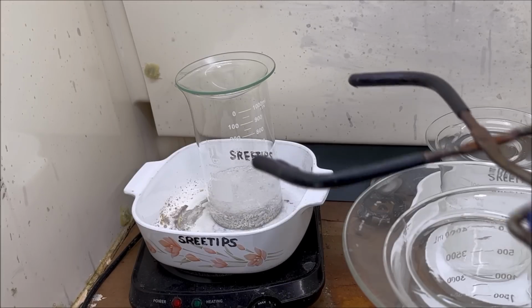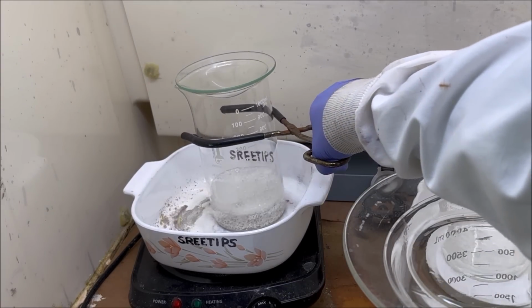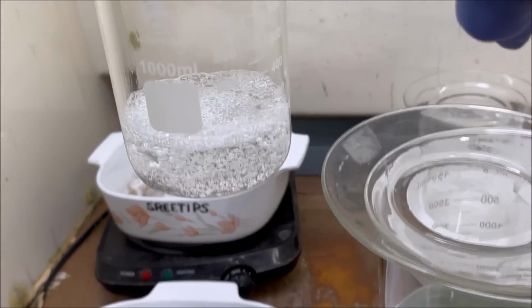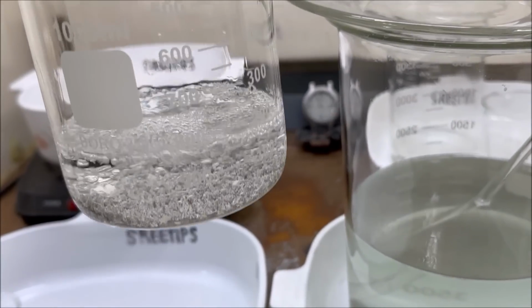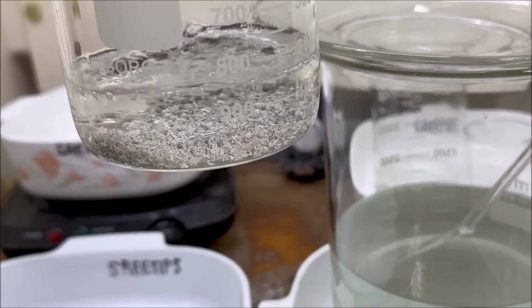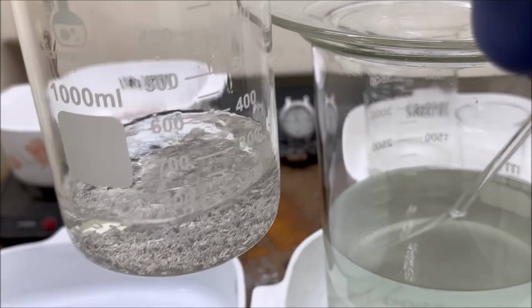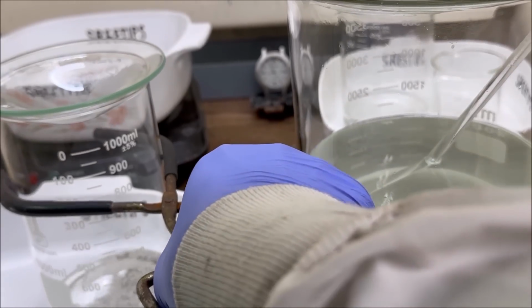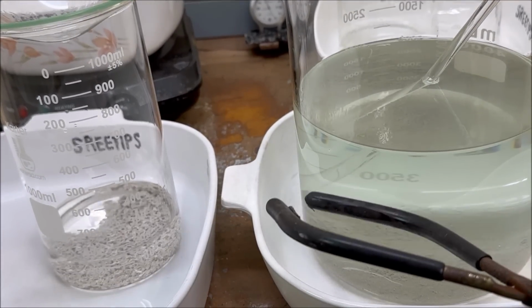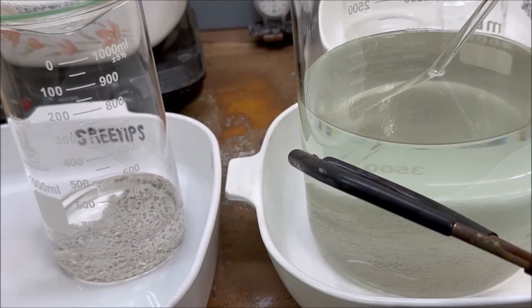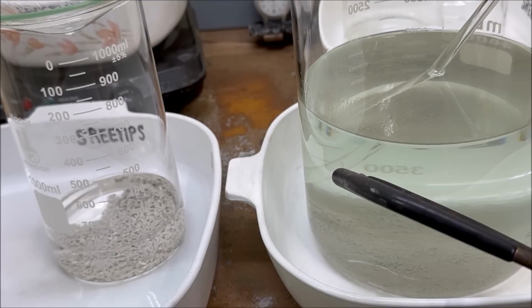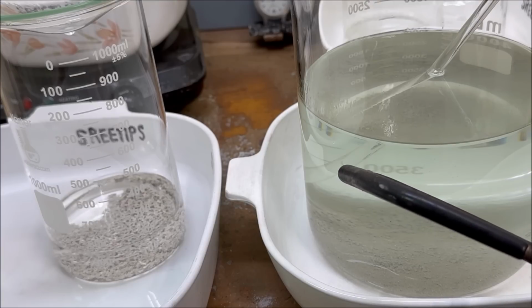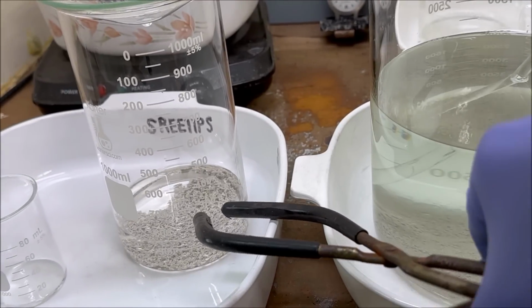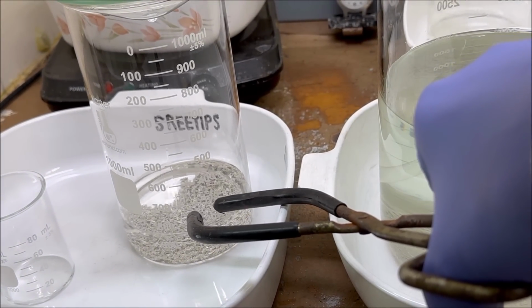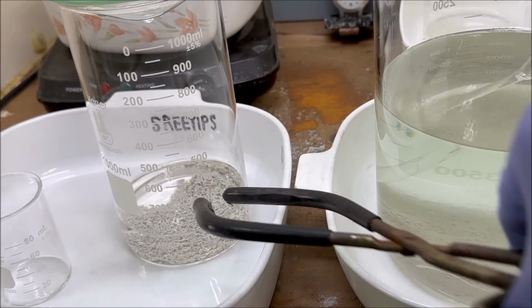This reaction is complete. There's no more fumes in here. This is a sample of my pure silver crystal from my silver cell. You can see it's colorless like water. And I did this to prove that the color that we see in this beaker here came from those pure silver bars. That's copper in there. So those 999 fine silver bars had a little bit of copper in them. The copper did not come from my pure silver. It's clear and colorless like water.